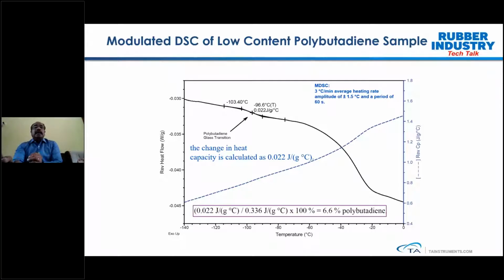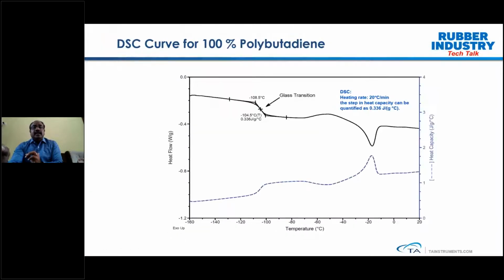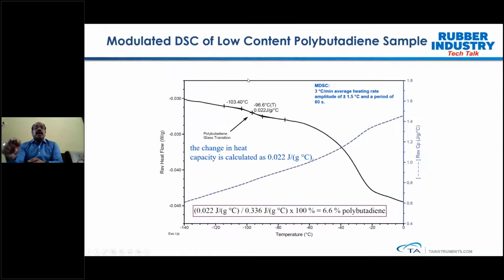And we could clearly see the step change, and we also quantify how much the heat capacity changes. If you go back to my previous slide, I hope you are all able to see it, the step change is well pronounced, and we get 0.336 joules per gram degree centigrade. This is the heat capacity change of 100% polybutadiene. In the mixture, we are measuring 0.022 joules per gram degree centigrade. If I take this ratio, I can clearly quantify even 6.6% polybutadiene present in the polymer, accurately, by using modulated DSC.